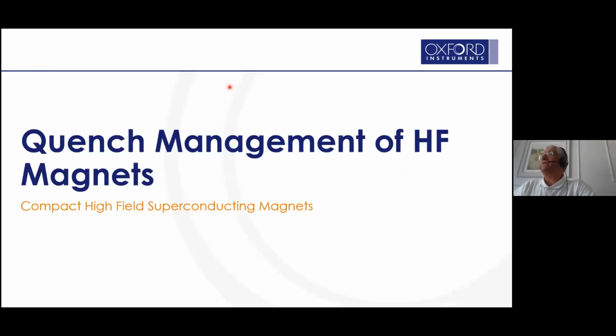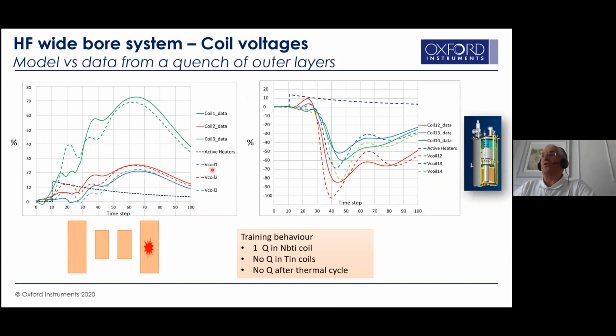One of the things I mentioned was quench management. This is a set of voltage traces we modeled and measured for one of our high field systems, showing how important it is to predict the performance of these systems to ensure that your quench is safe and the operation of your system is reliable and robust under various operating conditions. What I'm showing here is a NbTi coil quenching, pumping the tin coils, and the quench management activated to ensure that the voltages are within the capability of the electrical isolation of these coils.